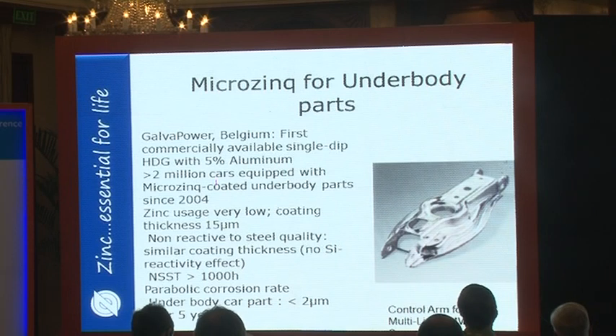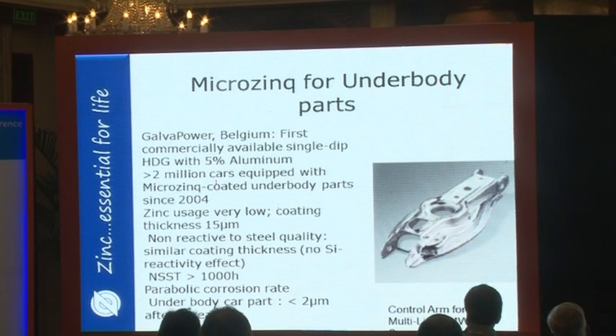It's not reactive to steel quality, so we can use silicon-killed steels and have no problem at all with the overcoating, and it shows a very low corrosion rate. So this has been a very successful development for high volume use of general galvanizing in Europe.